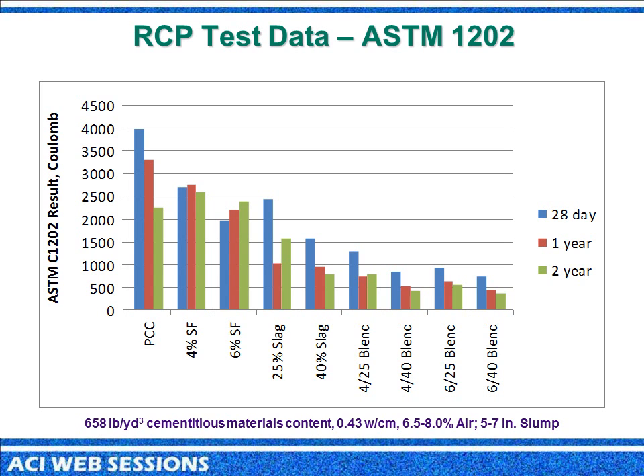When we look at the RCP test data, now we're starting to get a flavor for durability. But durability goes beyond this now. We're really looking more so long-term, what we would look at as service life. Now, the RCPs here, as we can see, the same chart follows at the bottom where we see our separated components. Now we're seeing our blends at the end.